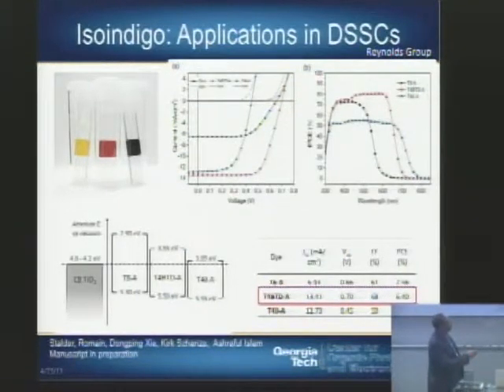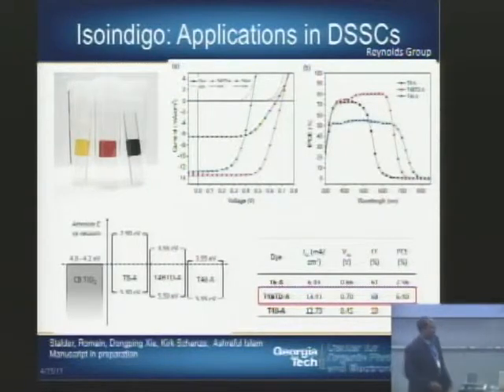And if you look at the incident photon power conversion efficiency, the reason why this mid bandgap polymer is slightly better is because the incident photon conversion efficiency is higher over this particular portion of the incident spectrum as opposed to the small bandgap polymer. So it gives it the higher power conversion efficiency. But nonetheless, there is a methodology and a toolkit here to create these polymers so that we can play around with or engineer this particular charge transfer process to try to improve the overall power conversion efficiency of dye-sensitized solar cells.